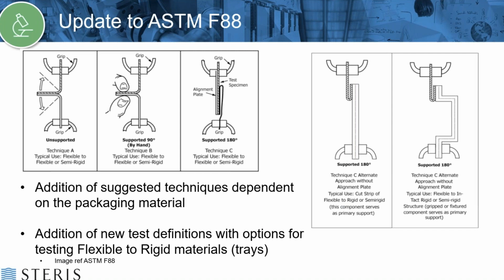So ASTM F88 is the peel test standard, and there's been some recent updates to that. There was an addition to allow for flexible to rigid material, so like a thermoform tray. Most people were using the standard for that type of testing previously, but the standard didn't specifically call it out. It now does. The other addition is suggested techniques depending on the packaging material.